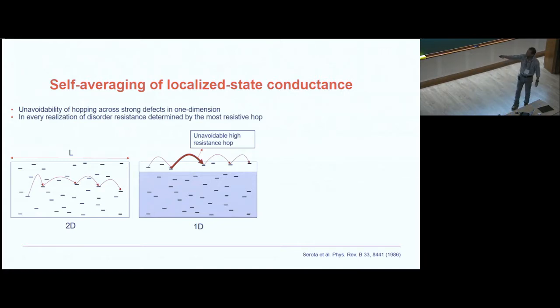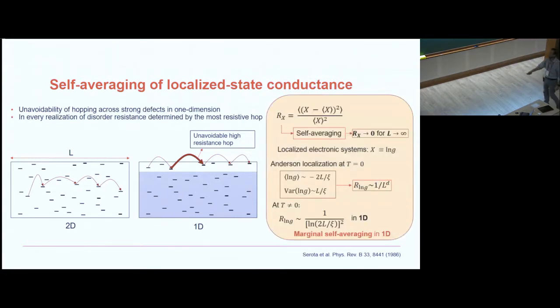So in 1 dimension, it's not possible. What happens in 1 dimension is that you are forced to move in this direction. You cannot move in the insulating bulk. So there's an unavoidable high resistance hop, which completely destroys the effect of the length of the system, or the system size. Very quickly, if I have a thermodynamic quantity, its fluctuation must go to 0 at large enough scale. Okay, so that's called self-averaging.